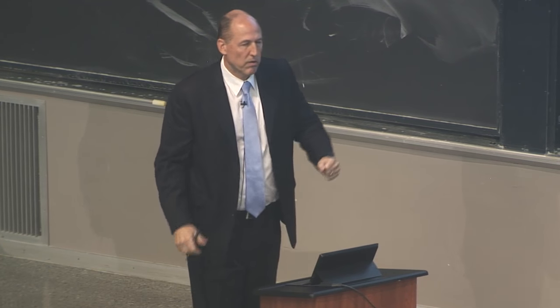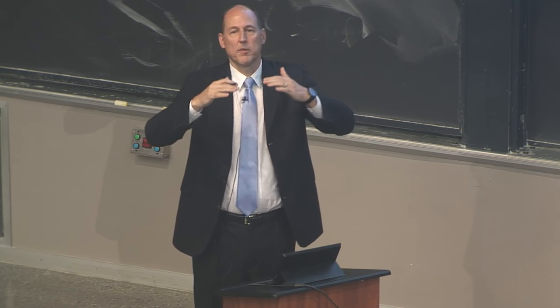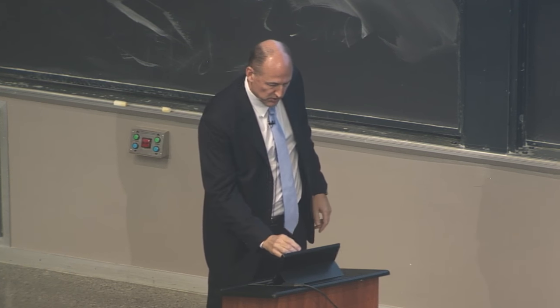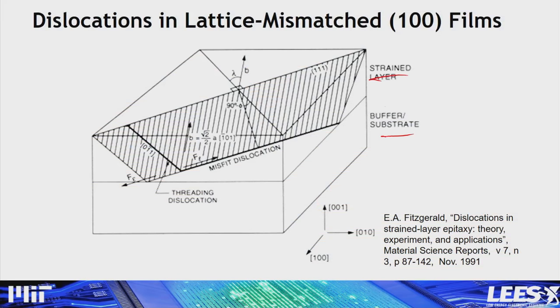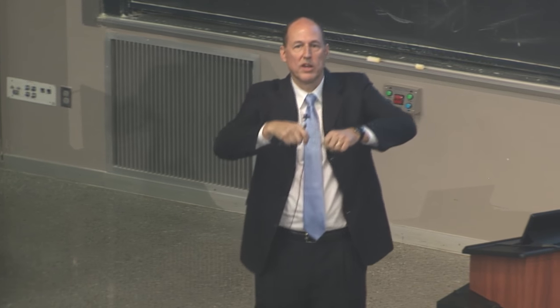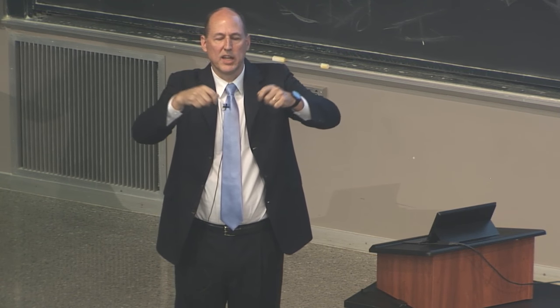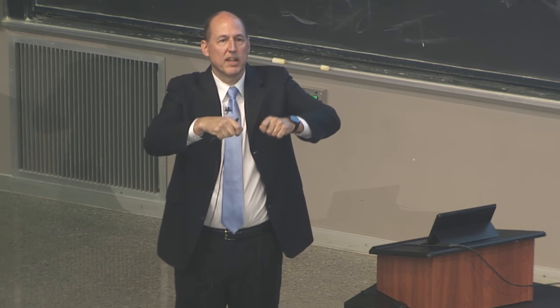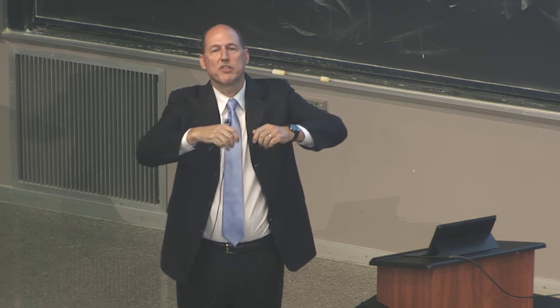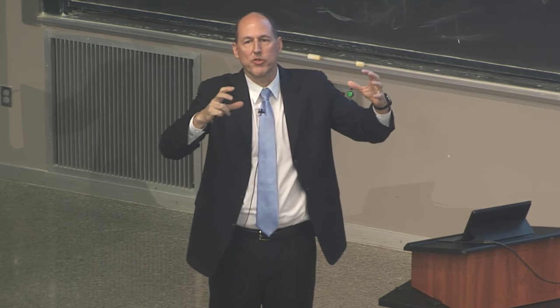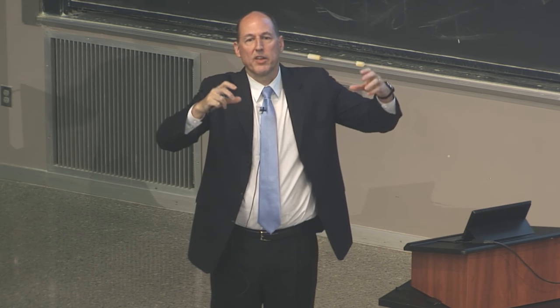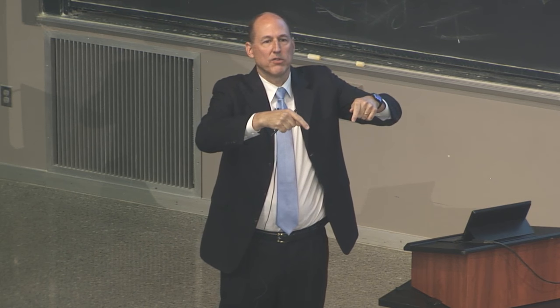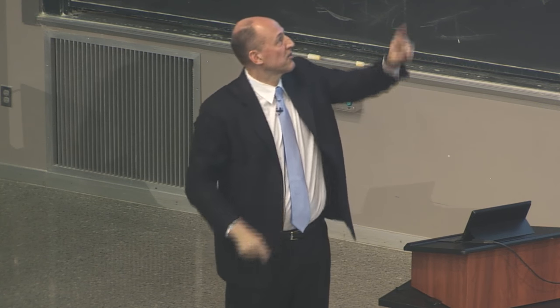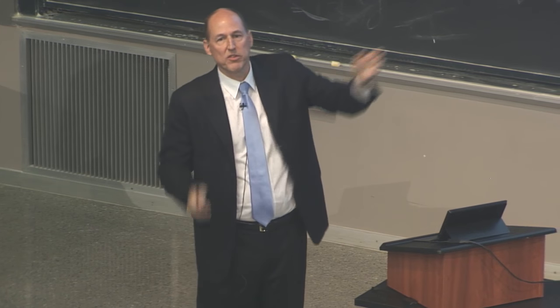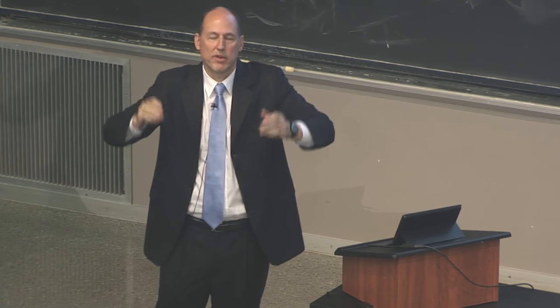So you've got to figure out, well, if I put a lattice mismatched material on top of this substrate, here's the substrate and here's the layer, there are two states you could have. If it's thin enough, all the atoms go down and they don't know that they're supposed to be at their bulk lattice constant yet, so they can be stretched to fit on that substrate template, right? But you can imagine eventually, if I grow thick enough, I'm building up more and more strain energy per area, and then eventually I can afford to inject things like dislocations, because when this comes in, it puts a half plane in the material, so it allows the layer to relax, right?